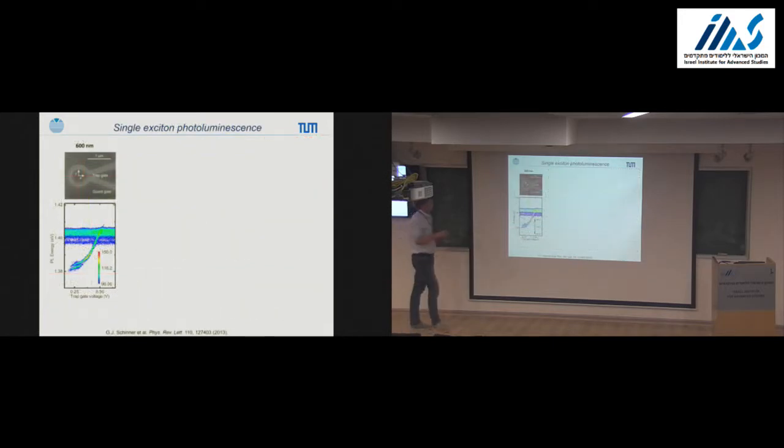And it turned out that we only found it for samples with a diameter of 600 nanometers for the top titanium gate. But this is very peculiar and depends very much on what kind of heterostructure you have. Because when you have a back contact which is very far down there, of course the profile of your top structure does not matter anymore. So you have to balance where you put your back contact, but also where to position your double quantum well.